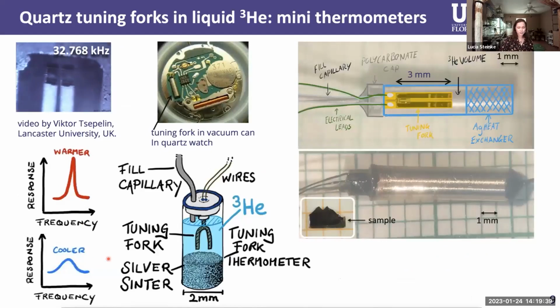And it turns out that the solution for that is found inside quartz watches. So the oscillators inside quartz watches are little tuning forks that have been used for a long time in ultra low temperature physics to measure the temperature of helium-3 baths. And I figured out that you could use the same technique to even measure the temperature of a small sample, because the tuning fork probes the viscosity of helium-3 liquid. And that's an intrinsic property of the liquid, meaning it doesn't depend on how much liquid is around the tuning fork.